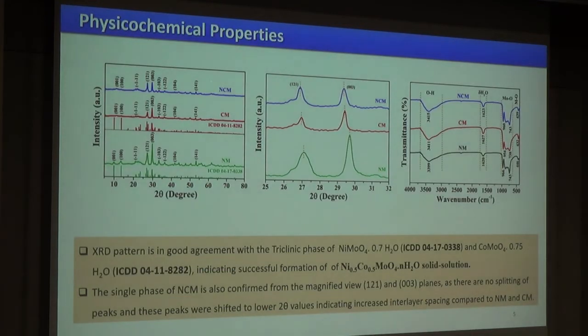Now the XRD pattern of only nickel molybdate (NM) and cobalt molybdate (CM) shows the formation of the triclinic phase of the respective materials, whereas in NCM both these phases are observed, and the magnified view shows that there is no peak splitting in NCM, which indicates the successful incorporation of cobalt in the nickel molybdate hydrate matrix. And further, the FTIR spectrum shows the OH stretching vibrations due to the hydrogen bonded water molecules, which indicates the presence of crystalline water molecules in this sample.